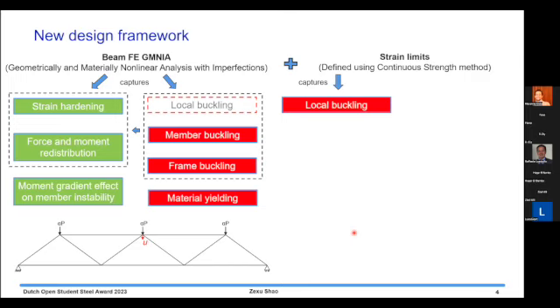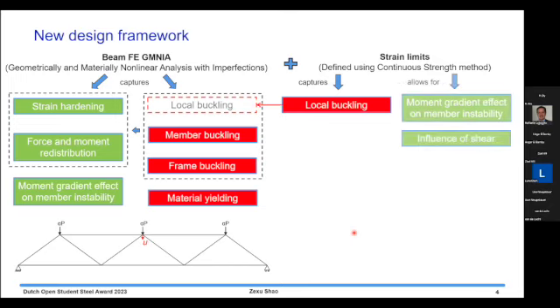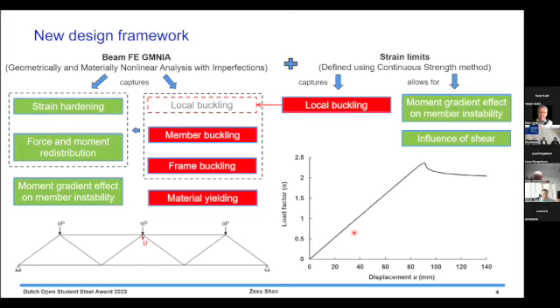So it's time to introduce our strain limit. The strain limit can capture the local buckling to fill the gap of the original beam finite element model. Additionally, it takes into account the moment gradient effects on member instability and also includes the influence of shear. So for example, with a beam finite element model with GMN analysis, we have the load to displacement curve. We have two cases. The first case is when the CSM strain limit is reached before the peak load, the ultimate capacity can be taken at the failure point. Or we could have the CSM strain limit reached after the peak load, and for this case, the ultimate capacity should be taken as the peak load.